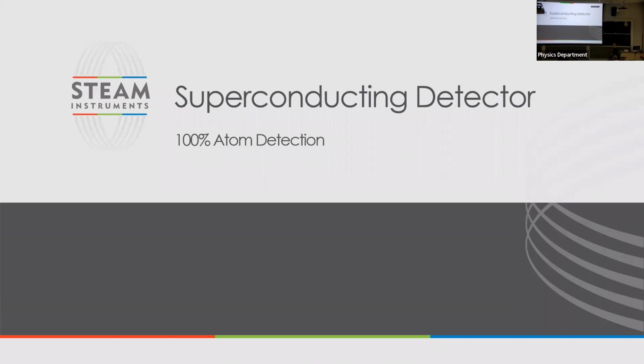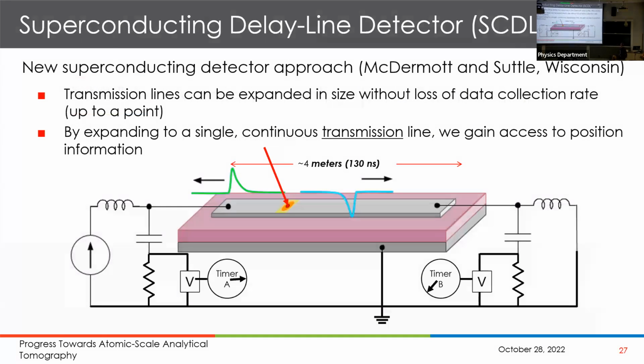All right, I want to say a little bit about the technology on the detector first, then on the electron microscope, and then I'll say a little bit about some potential applications. At any rate, just to give you an idea of how one of these superconducting detectors would work, it's based on the concept of a delay line detector. And this would be, let's say, a micron wide line of niobium, which is a superconducting material at 9.2 Kelvin. And it'd be about 40 nanometers thick. And if you put a supercurrent in that at 5 Kelvin, about half the critical current density, then you have this wire just sitting there superconducting.